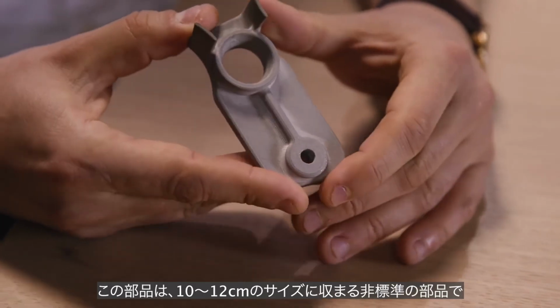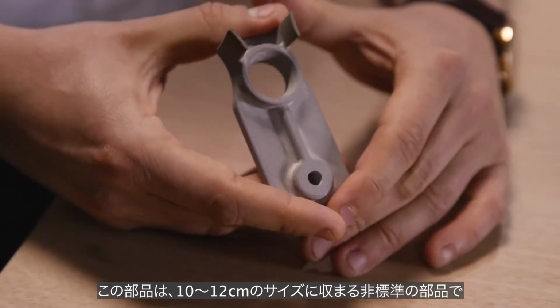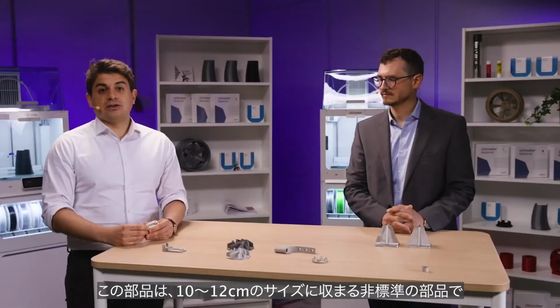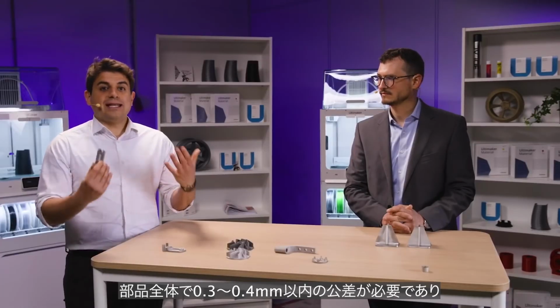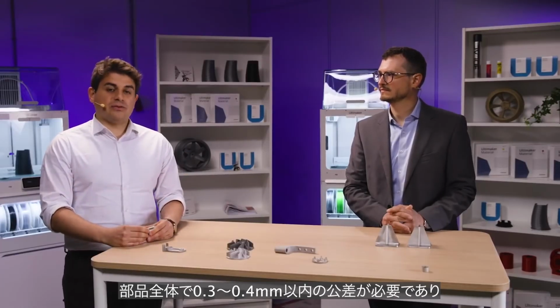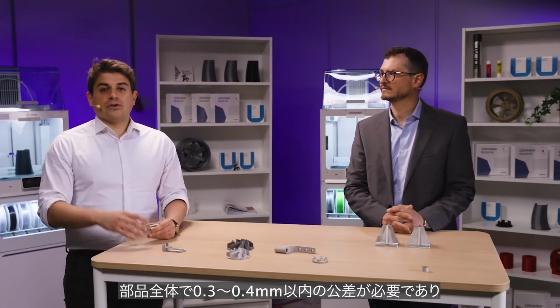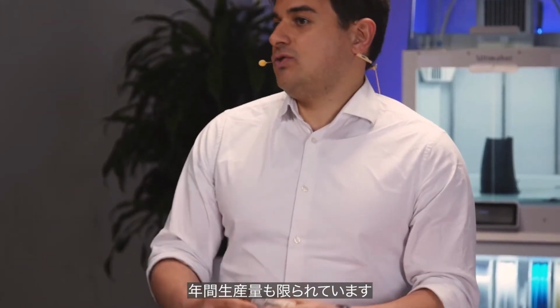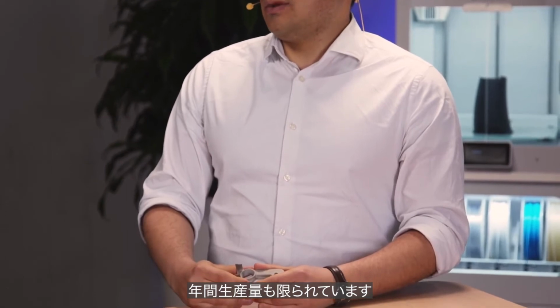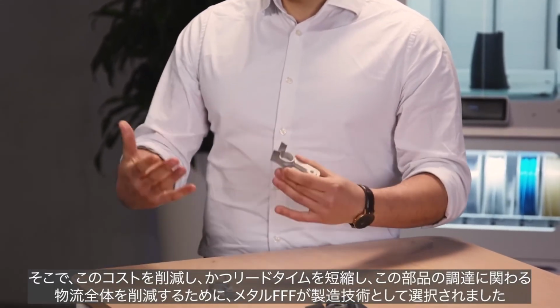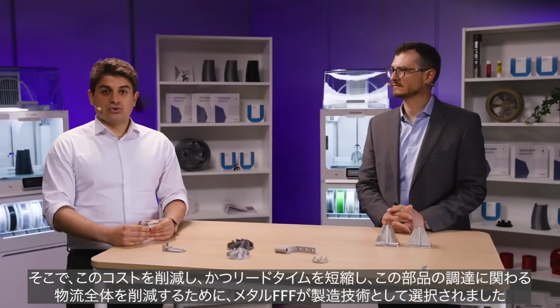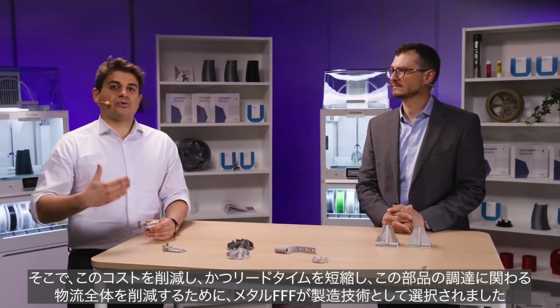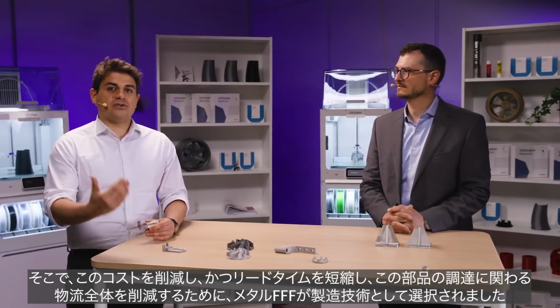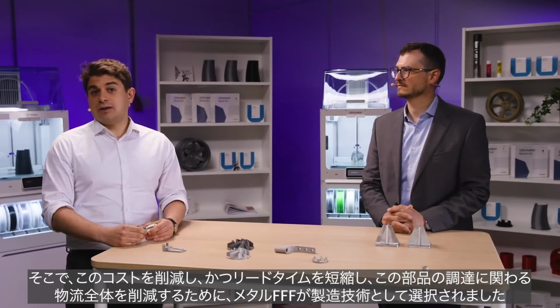This is a part that fits within the 10 to 12 centimeter size, is a non-standard off-the-shelf part with the need for tolerances within 0.3, 0.4 millimeter over the whole part, and a limited amount of units that need to be produced per year. Metal FFF was therefore selected as the manufacturing technology to do this cost out, but also to reduce lead time and the whole logistic around the sourcing of this part.